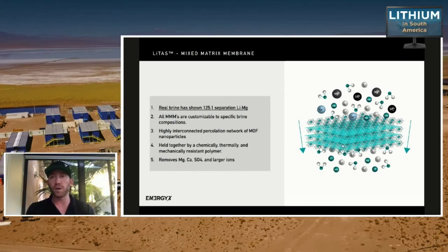And this is essentially what we've been working on for the past 2 years, building something that has high separation of lithium from magnesium. It has high flux or permeance so that the brine can flow through at an acceptable rate. And it has high stability so it lasts for hundreds or thousands of hours, which is the point we've gotten to in the laboratory, with no degradation. What the current mixed matrix membrane that we have formulated does is it separates the larger divalent ions. So in addition to magnesium, we separate calcium and sulfate. We're still working on the next generation, which is generation 2 that I'll talk about, that is a monovalent separator. So it separates lithium from sodium and potassium.